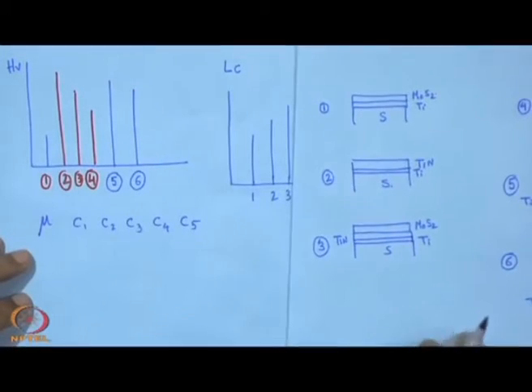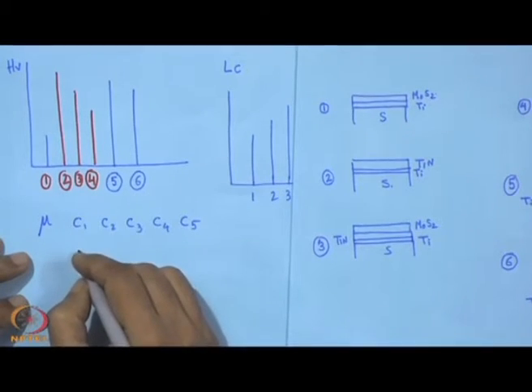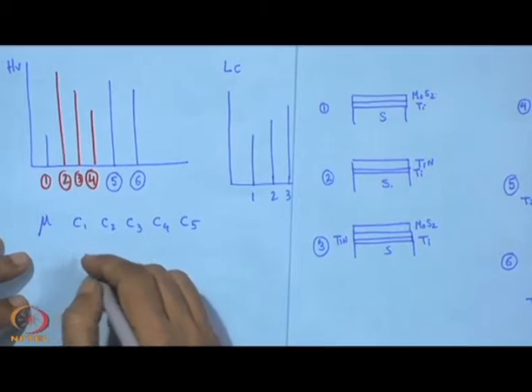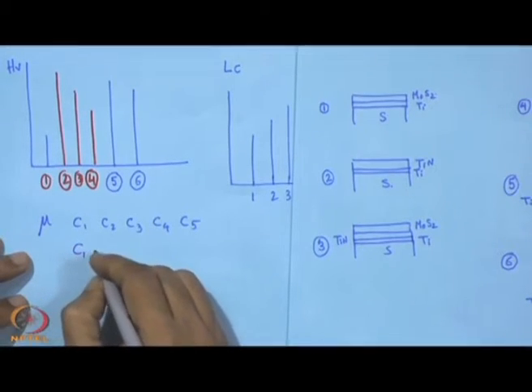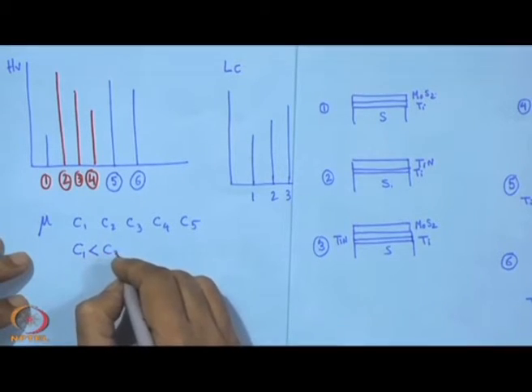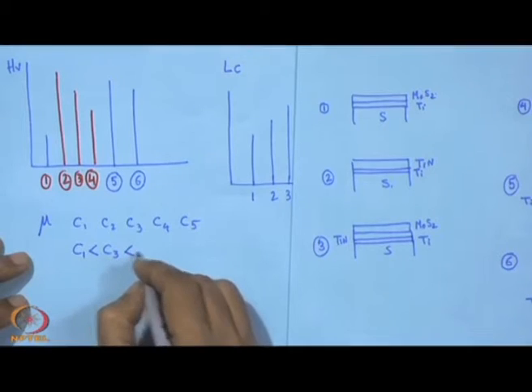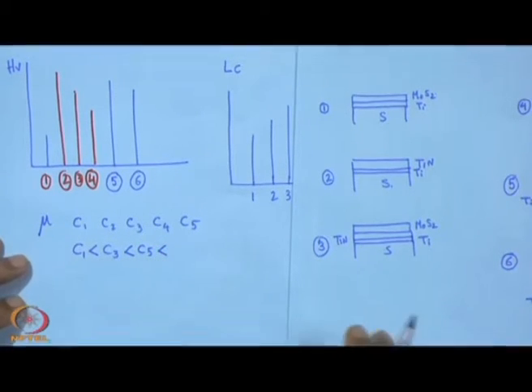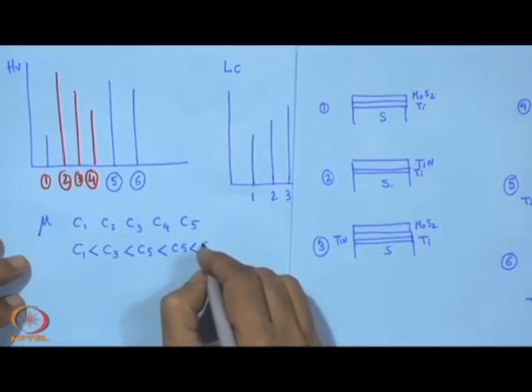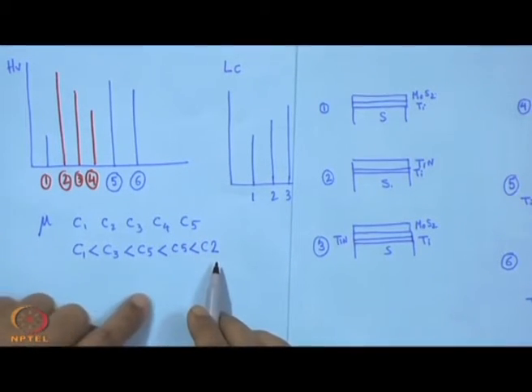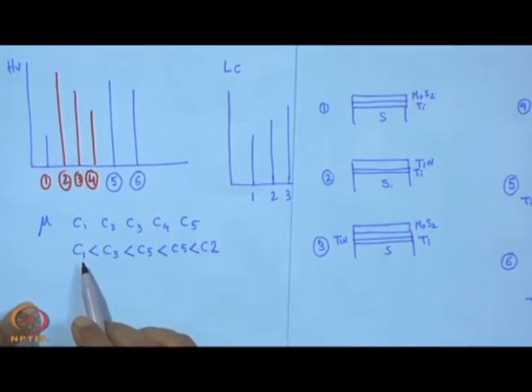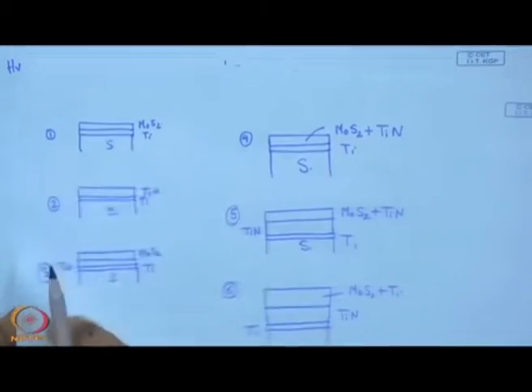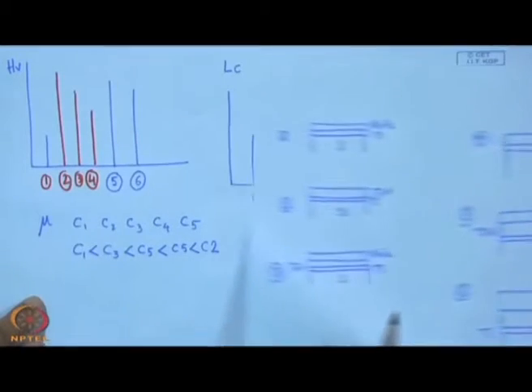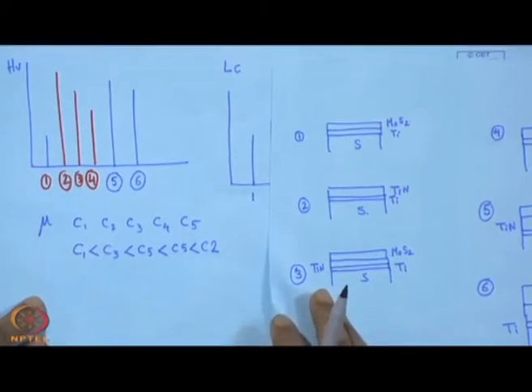So, in this case what we can show is that C1 has the lowest coefficient of friction, then C3 is the second lowest, followed by C5 and finally C2. So, on that scale, C1 gives the lowest value of coefficient of friction because of the MoS2, and TiN is not a lubricating coating, though it is a wear resistance coating.